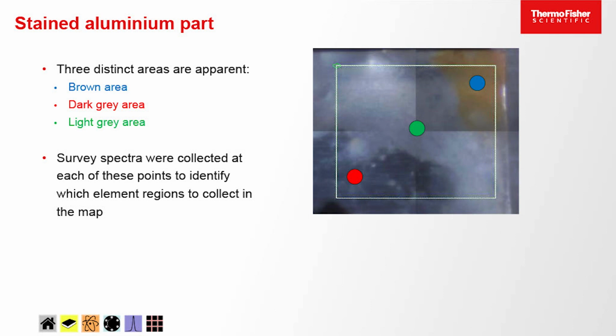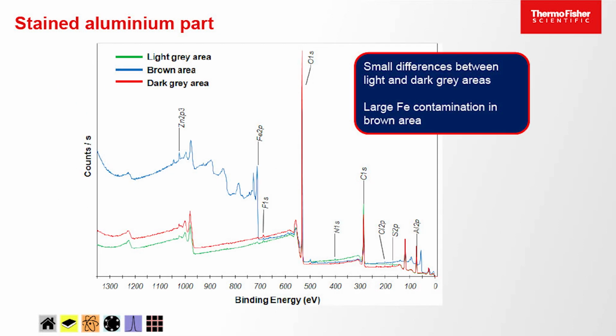And first things first, do some point positions and collect a survey scan to understand which elements are present. So we have the light grey area is the green spectrum, the brown area is the blue, and the dark grey area is the red one. And the light and dark grey ones look pretty similar. There's not a huge amount of difference there. And obviously there's a big difference with the brown area where we can see lots of iron present. When I said the brown discoloration, probably a good guess would have been some iron oxide on the sample. So that's what we can see. We also see a little bit of zinc there as well.